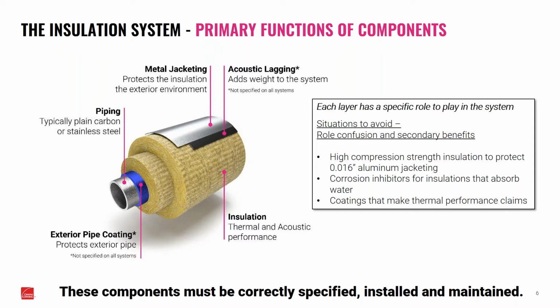Then finally, there's coatings that make thermal performance claims. Anytime coatings are there to protect the pipe, there are some coatings that have been used that do reduce the surface temperature a little bit, but even just using a minimal thickness of insulation will provide more thermal benefit than a coating that you're going to apply that is pretty technical. You have to make sure you do adequate surface prep, make sure you coat properly. It does take a little more time as you wait for the subsequent layers to dry as you're doing it.